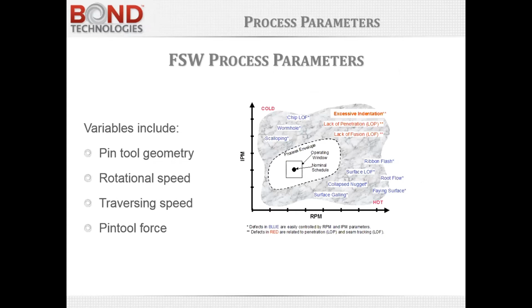So the process parameters start with the pin tool geometry, and then rotational speed and traverse speed and pin tool force are the three parameters that really affect the elevation of temperature, which then affects the flow stress of the material and results in the mixing of the material. This little graph shows the spindle speed on the horizontal with the feed rate or traversing speed on the vertical. And this is a kind of a useful graph to show what some of the areas outside of the ideal process window will look like and what the result is. So part of the exercise in productionizing this process is similar to many other processes where an experimental design is typically used to define the process window and the operating point within that process window.